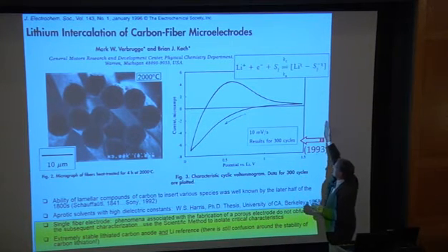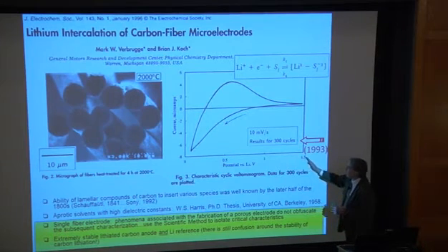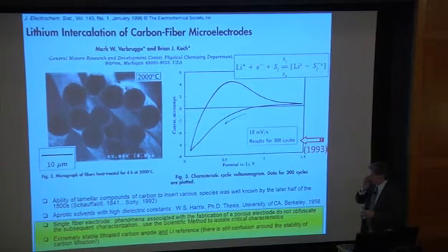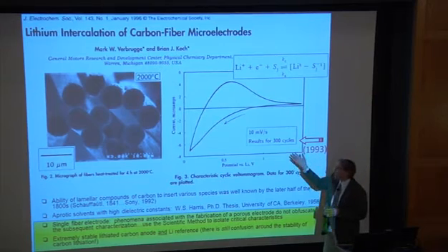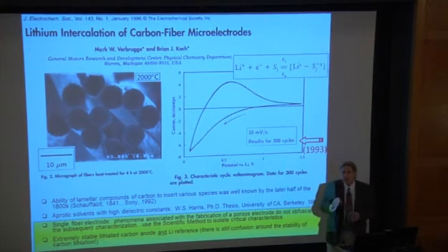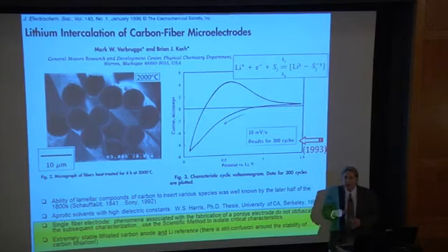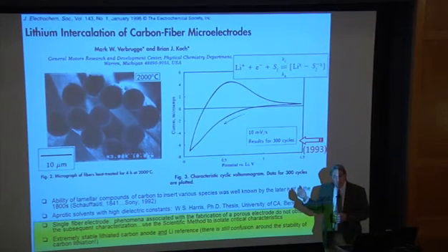And over here, you'd eventually come to the point where you have no lithium in the system and your potential is more of an oxidizing potential. The point is this was recorded on an oscilloscope. It's 300 cycles. It's just rock solid. The cycles plot over one another. And this is what we used to convince management the active material works.